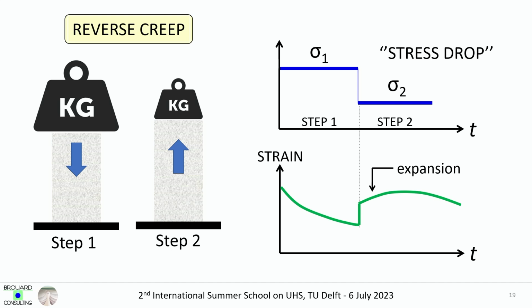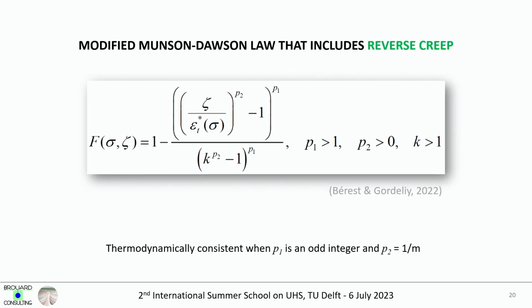Something which is quite uncommon with rock is what we call reverse creep. This is a kind of special feature of rock salt. If you consider, for instance, a salt sample and you apply a load, sigma 1 here, for a while, and then suddenly you remove some of the load. You keep some load on the sample, but you remove some part of it, and you can observe an increase of the height of the sample. It means that the sample is able to provide some energy back to the system, which is a bit special. And this is something that Pierre Berest was working on before he passed away, and he determined this modification of the Munson-Dawson law that takes into account this reverse creep. He spent a lot of time on this because he wanted a formulation that is thermodynamically consistent. But this has not been tested yet.